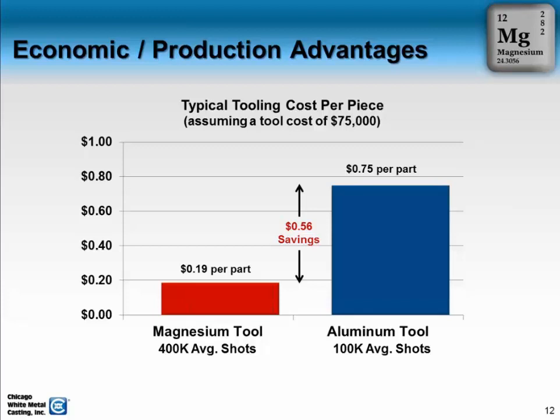For magnesium, we see about 3 to 4 times, probably closer to 4 times the die life. So for the magnesium die, you're going to get about 400,000 shots. When you look at that over the $75,000, it drops the per part cost down to about 19 cents. So this is one factor where you can see some advantage of looking at magnesium versus aluminum and what the part price savings would be over the life of that tool. In this case, it would be about a 56 cent savings over the life of that tool.